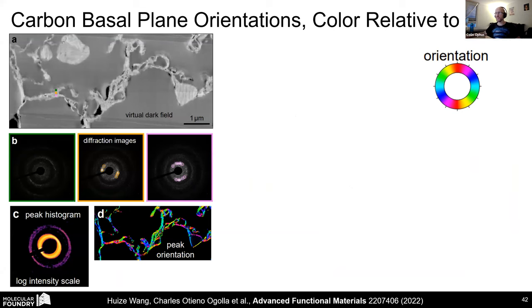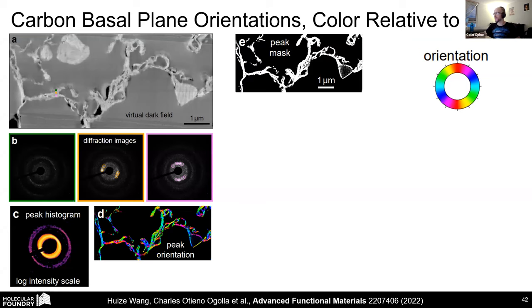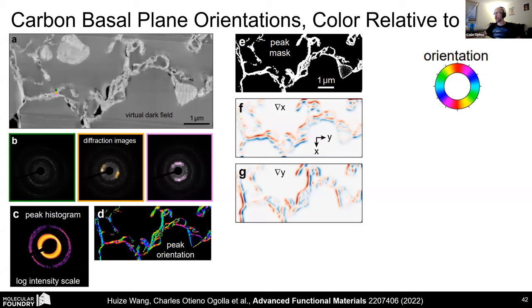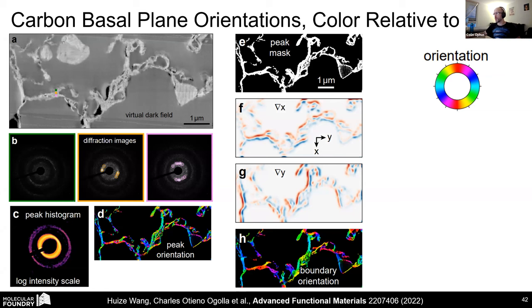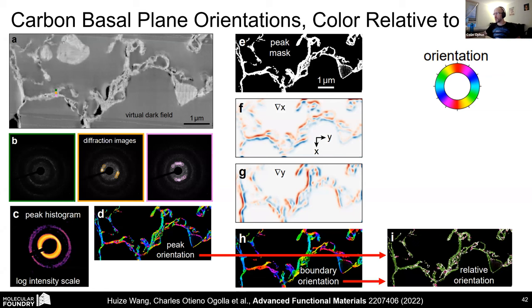But the hypothesis was that in the darker gray regions here, where the glue is, the sort of hollow regions of this material, the basal planes would be aligned to those holes, essentially. In order to test that, we did a bit of data analysis, found where all of the voids were and where all the carbon regions were, calculated the normal derivative of those materials, and pulled out the boundary orientation map.